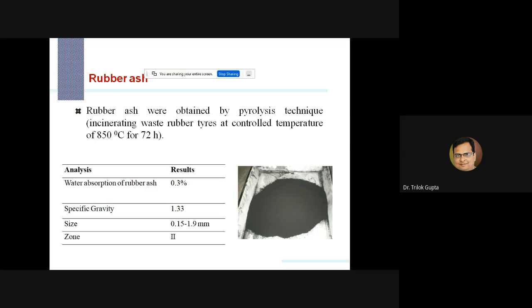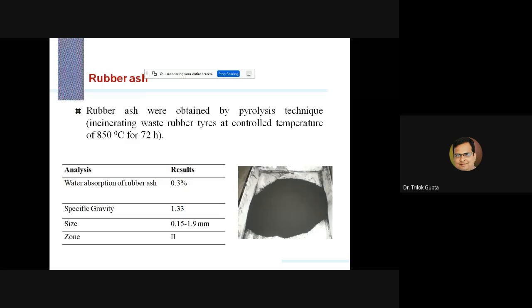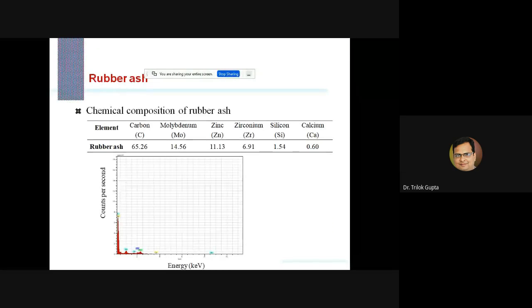Basically, in this study, we used two types of waste rubber tire material. First was the rubber ash, which was obtained by the pyrolysis technique, that is, incinerating waste rubber tires at a controlled temperature of around 850 degrees Celsius for 3 days. The specific gravity was only 1.33, size was between 0.15 and 1.9 mm, and absorption was only 0.3%. The chemical composition has a carbon content of around 65%.